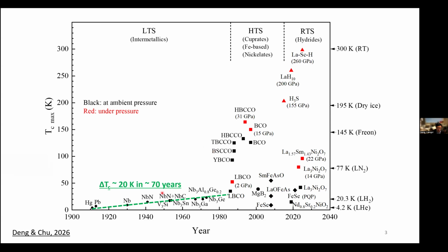But of course, this also brought people some confidence challenge: if we're really moving at this rate, when are we going to reach room temperature? That seems to be not that hopeful, right? Fortunately, in 1986 and 1987, we do see a quantum leap in the TC enhancement. People broke the 30 Kelvin limit, and especially YBCO broke the 77 Kelvin liquid nitrogen temperature. So that really was a gold rush time for high TC at that time. It's very exciting, a lot of interesting stories. More recently, by recently I mean the recent 40 years, we see a TC increase of 200 Kelvin. That's very optimistic, very promising.